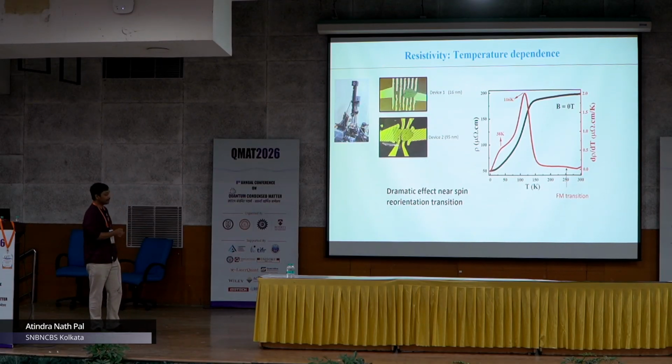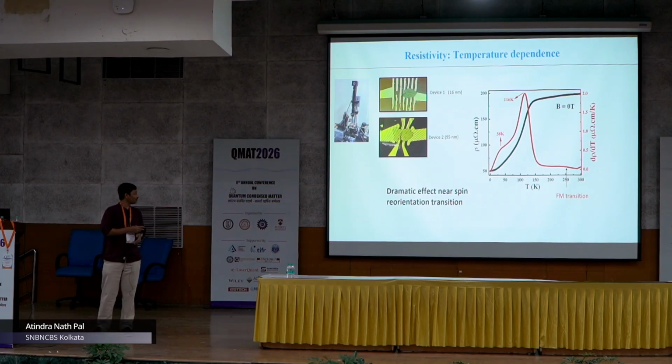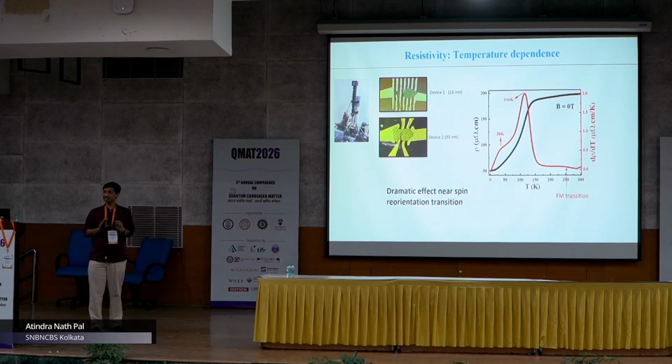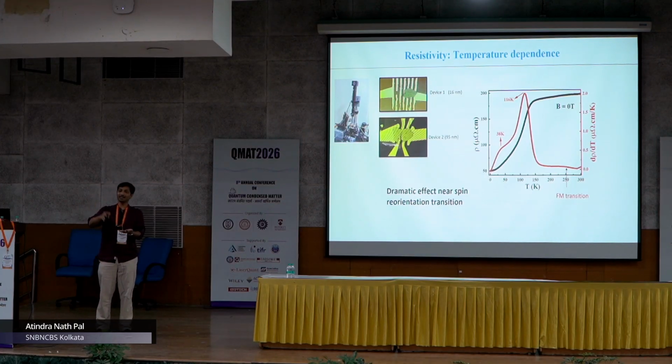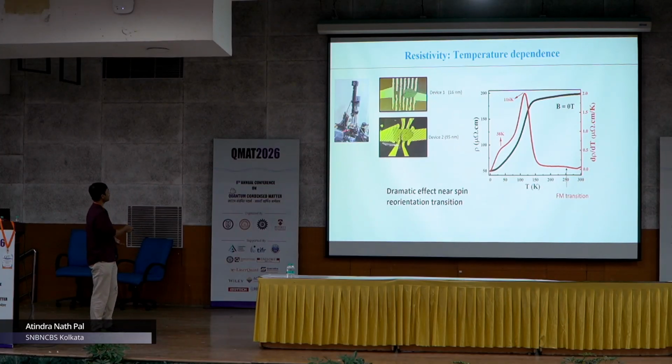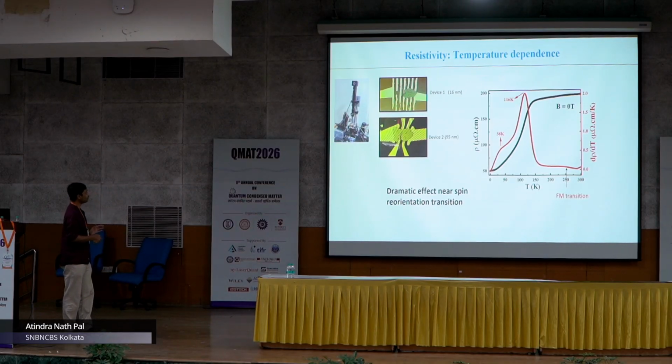So what we have done is prefabricate the contacts, and we found that these materials are stable up to, let's say, half an hour to 1 hour, more or less. So after several trials, we just made the contacts, and then within half an hour we exfoliate and put the flake using this dry transfer setup, and then we encapsulate with PMMA or some other resist. Okay. In this way we found that it can provide a good electrical contact, and we have done measurements from a few-layer flake of 16 nanometer to the bulk limit of 95 nanometer. It's not like graphene that you can exfoliate very easily, but it's exfoliable.